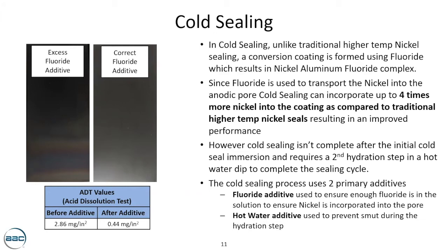isn't one you'll be fighting with a cold seal, because the cold seal bath in that first step is designed to do one thing and one thing only, and that is pump that coating full of nickel as much as possible. And in doing so, you build a very robust anodic pore that is not hydrated, but filled to the brim with nickel.